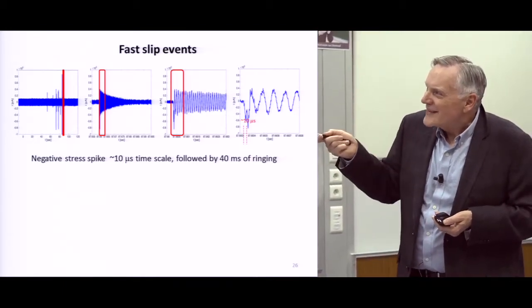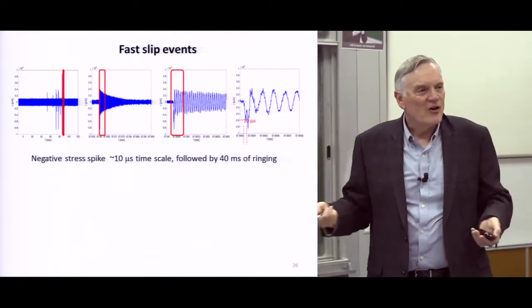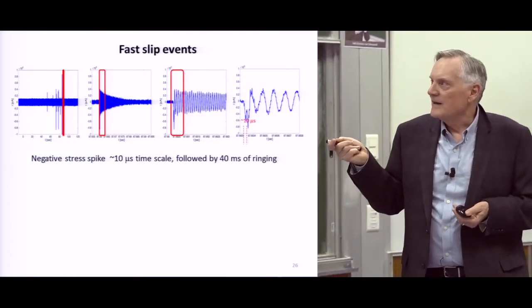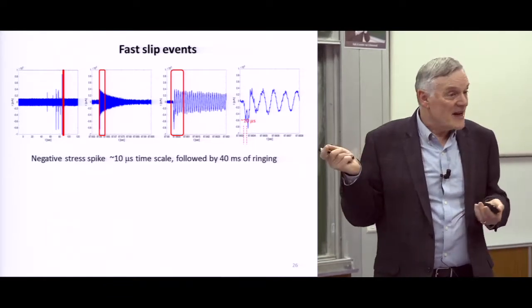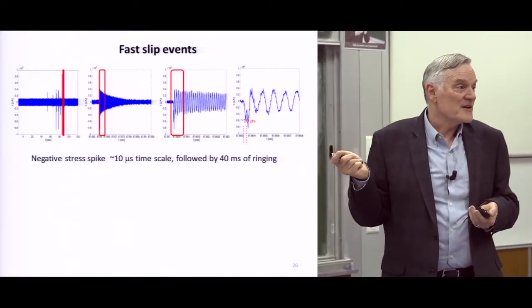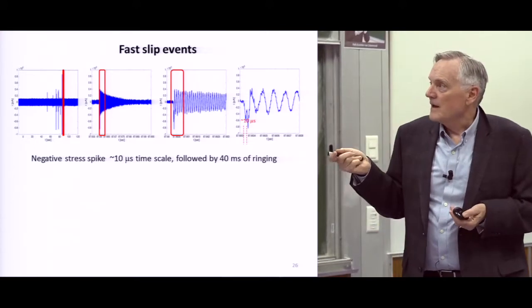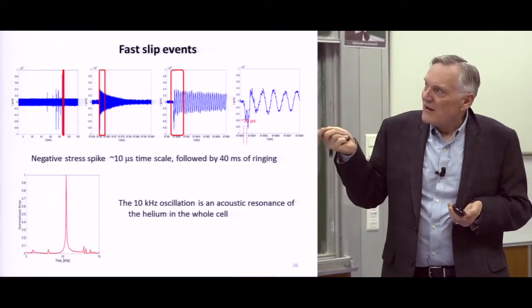So it's about a 10 microsecond event followed by a long ringing. But unfortunately, that's also the limit of our preamp, 10 microseconds, so it might be faster. What's the 40 milliseconds of ringing? Well, you can Fourier transform.